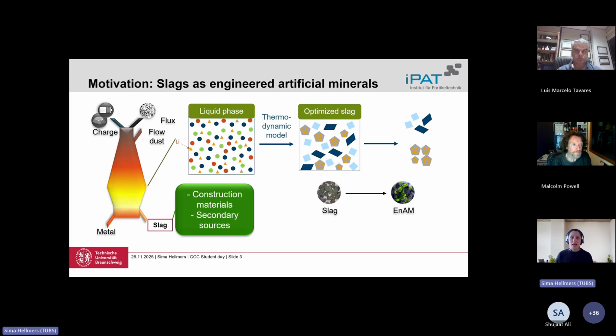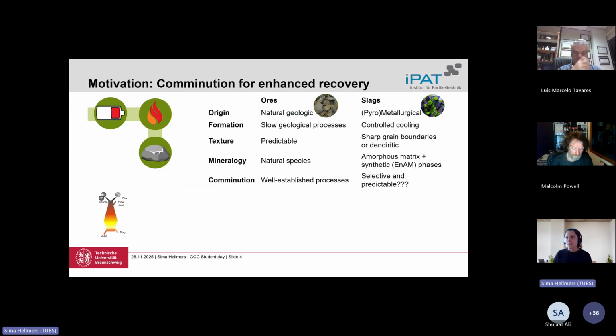To achieve this, there was the idea of engineered artificial minerals. That is, we have this slag that is really hot, around 1000, 2000 degrees. So we use thermodynamic modeling and we control our cooling so we can have our target elements in certain phases. Then using optimized comminution and liberation methods, we can get to our target particles. So it looks a bit like what the ore industry is doing, but it's not that easy, and I will tell you why.